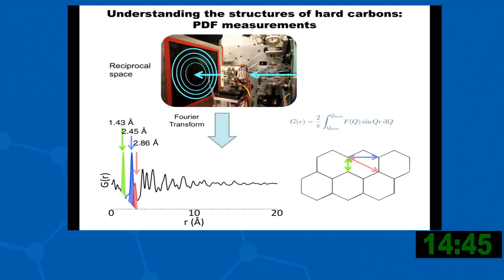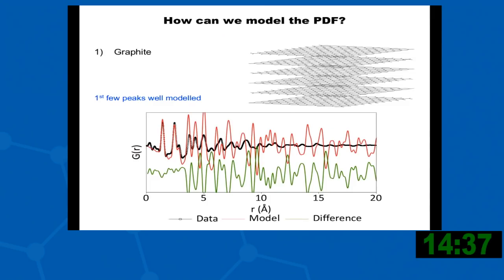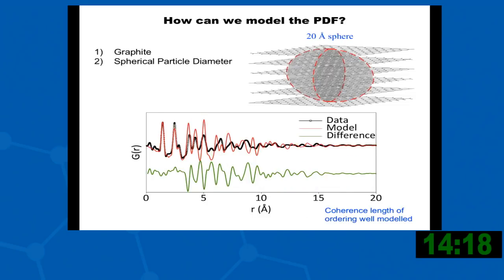So let's go back to our PDF method. Remember, we're taking a Fourier transform of the diffraction or total scattering. And now what I want to do is show you how we can model these data. This in black is the experimental data, and in red is shown a model of the data against a normal graphite model. You can see that the first two peaks might be well fit, but the long-range structural data is terrible, and so the difference is shown in green. If we then think about the sizes of the coherence length, so let's make a 20 angstrom spherical particle, you can see that we get the coherence length well modeled, but we still have a terrible fit.